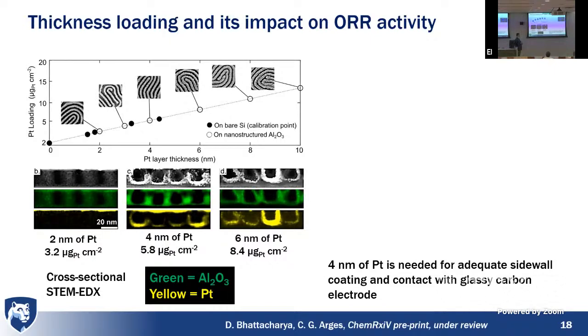over optimistic. So we went ahead and put down 2 nanometers here, and we did microwave digestion followed by ICP-OES to quantify the loading. These are very low loadings, micrograms per square centimeter of platinum. We did this cross-sectional STEM EDX imaging here. So here's our block copolymer structure. This is actually the final structure, and we can image the elements. So we see the aluminum, but we just see the platinum at the surface. We don't see it coating the sidewall, okay?